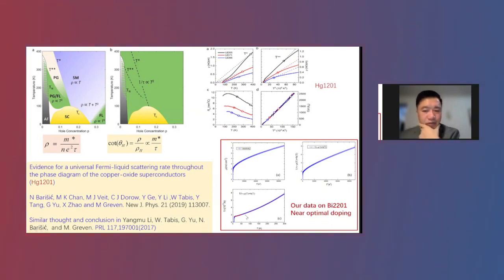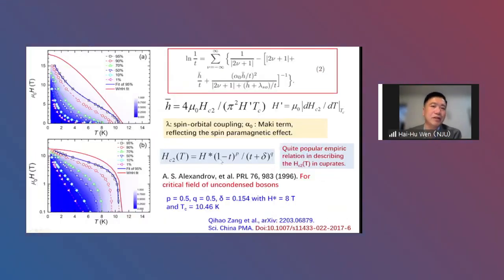And we follow the same way in our sample. We found that even when we just calculate this 1 over tau by multiplying by this charge carrier density, the temperature dependence does not show this quadratic behavior. Instead, we see this still rather linear in the low temperature region, okay, for this dissipation. So our sample seems different from the Mercury one.